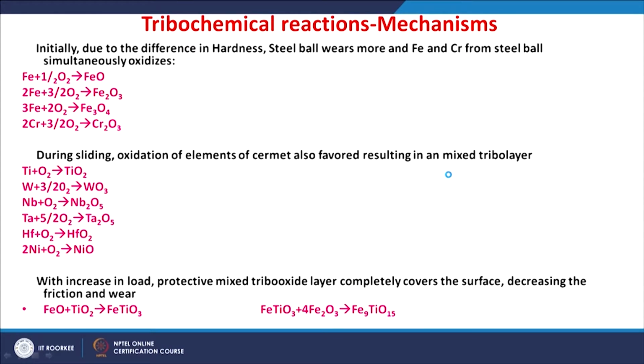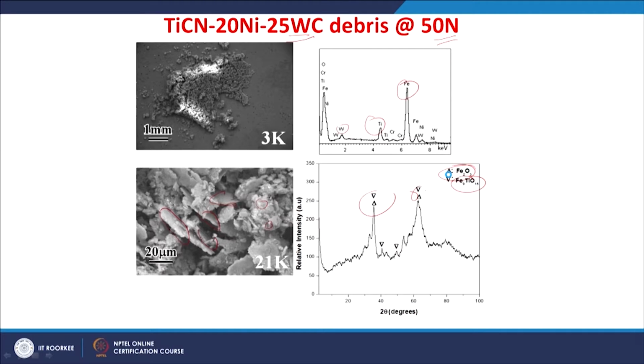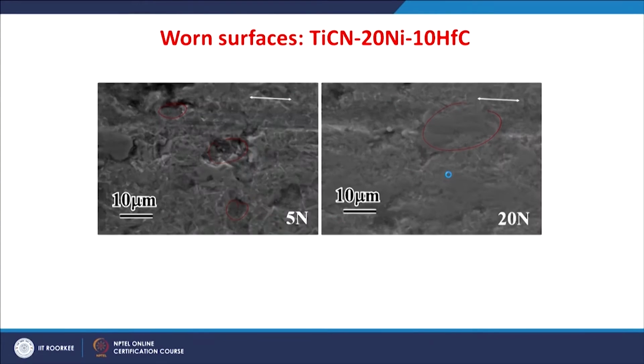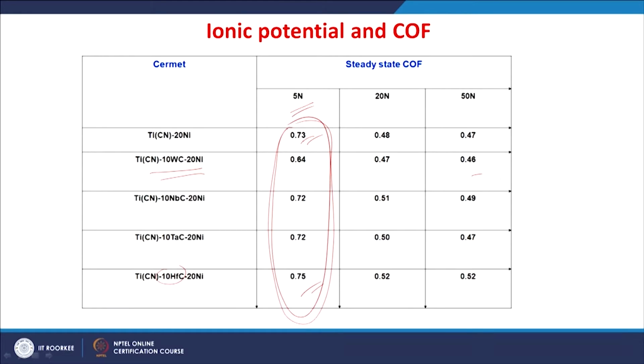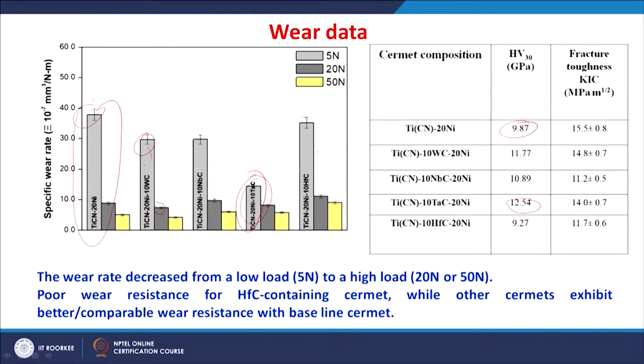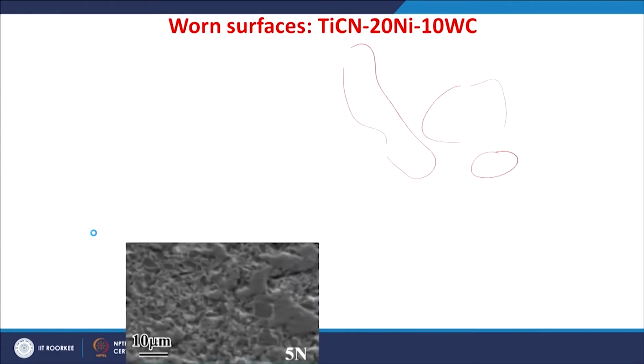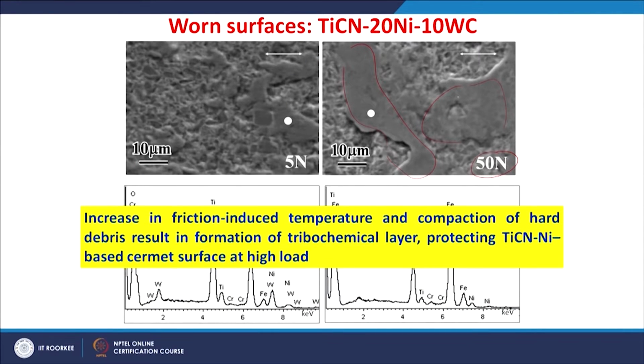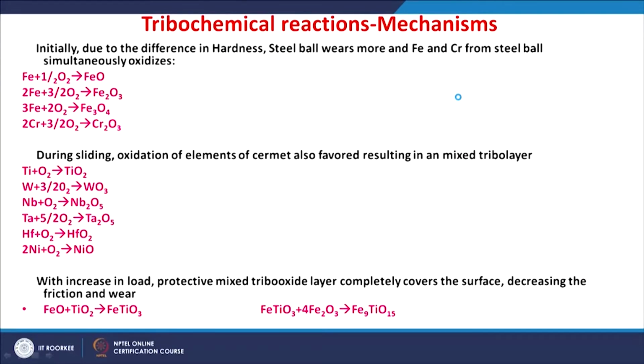So, all these results can be understood by the tribochemical reactions. The very important observation so far is that at lower loads the friction is high and at higher loads it is less, and similarly at lower loads the wear is high and at higher loads the wear is less. So, at higher load there is a domination of the tribolayer, whereas at lower loads it is more or less removal of the material by mechanical fracture. So, it is now understood that at lower loads it is only the mechanical aspect which is contributing to the wear, whereas at higher loads it is the tribochemical layer.